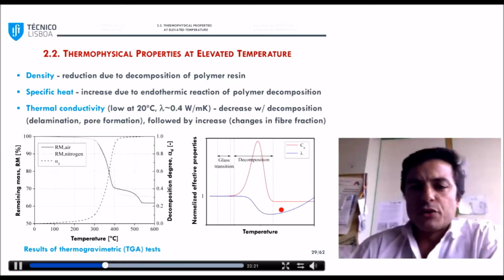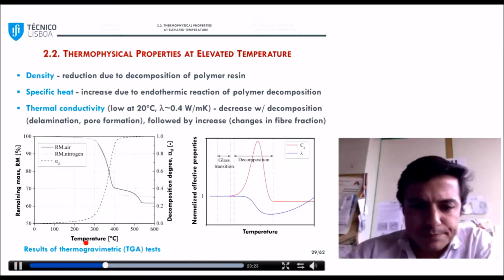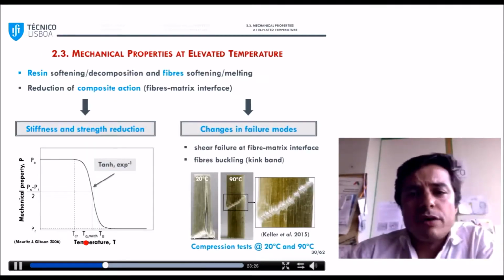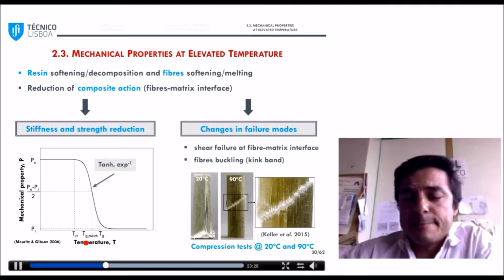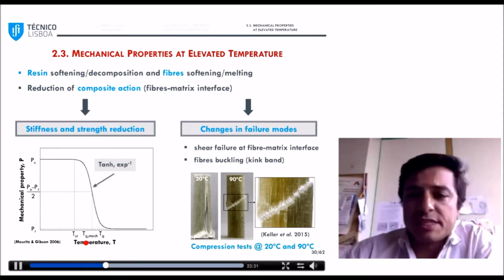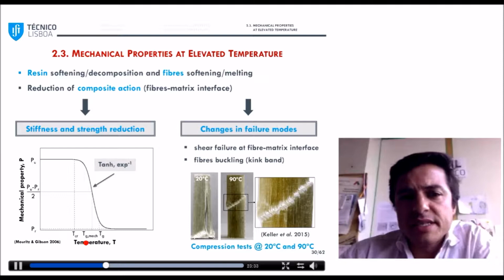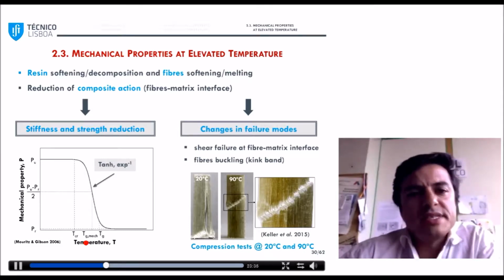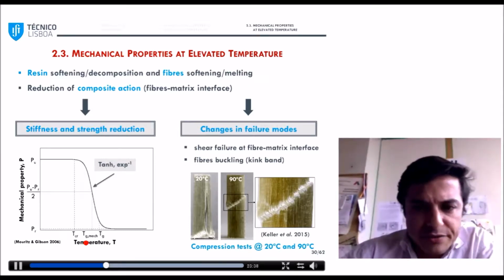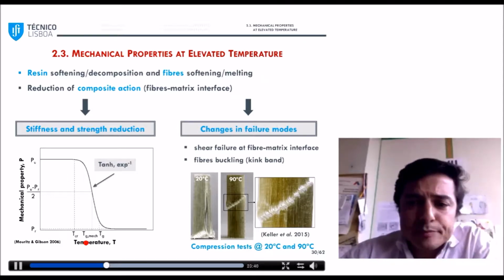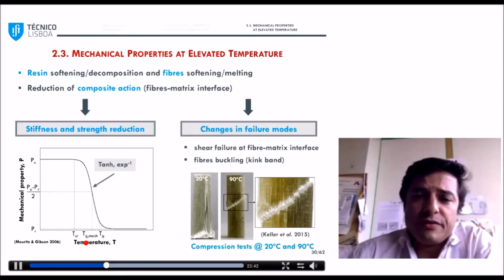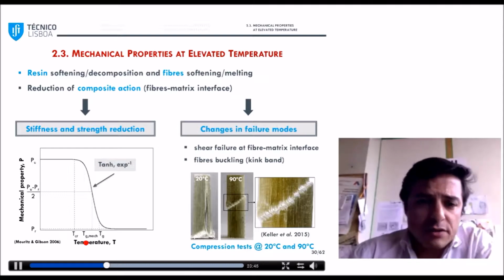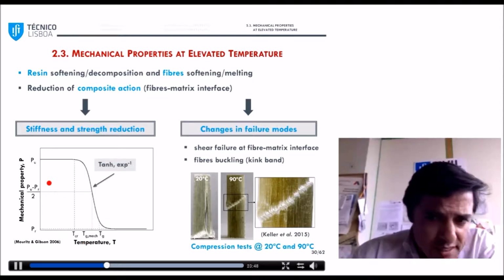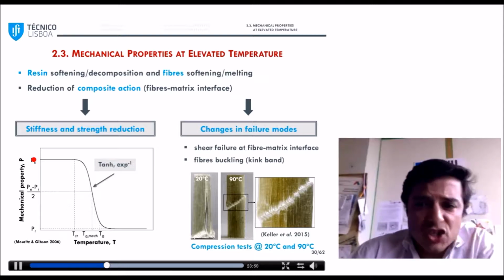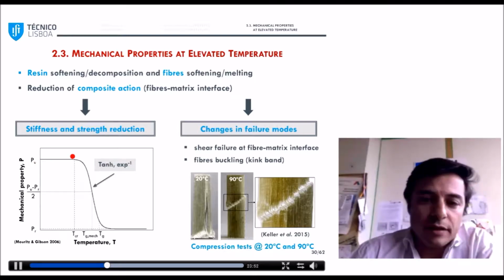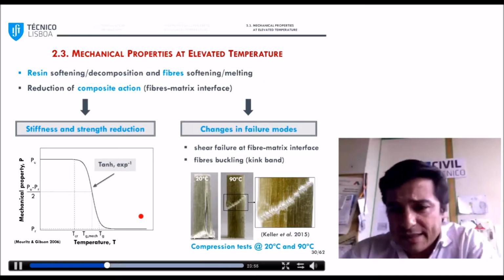And then it progressively increases due to the increase of the fiber volumetric fraction. Now, for the mechanical properties, we have the degradation of the constituent materials, the fibers and the matrix, and also of the composite action at the fibers-matrix interface. Consequently, we will have a reduction of the stiffness and strength properties of the materials. And as you can see in this picture here, the reductions typically follow a sigmoidal pattern.